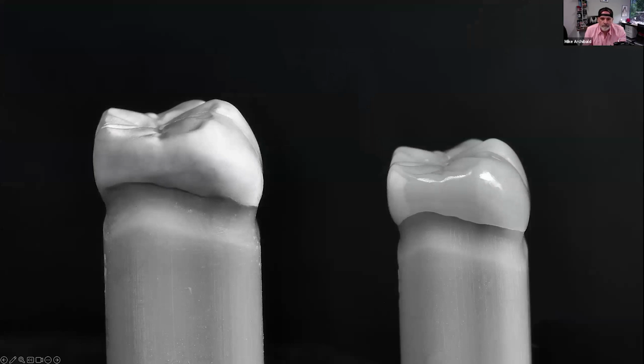So on the left, we have your enlarged die with the green state, and on the right, this is straight out of the sintering oven, this nano zirconia here on the right. That on the right is straight out of the sintering furnace, but that's hit with speed polish only. Also, no glaze on that crown on the right. No, we aren't glazing here. And those margins look absolutely beautiful. Nice seal. Everything's going to look great.